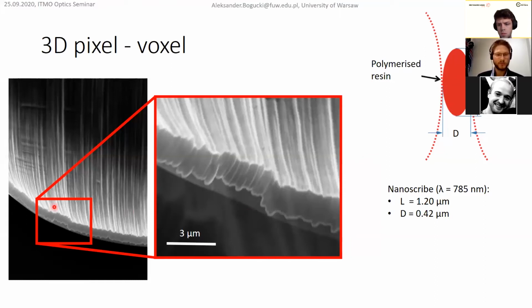So here are some scanning electron microscope photos of, let's say, a destroyed structure. And here you can see these ellipsoids, elliptic-like shapes. And so these are polymerized voxels. And yes, this voxel has the shape of an ellipsoid. And in our case, when we use this wavelength of laser, it's usually 1.2 micrometers in height and 420 nanometers in width.